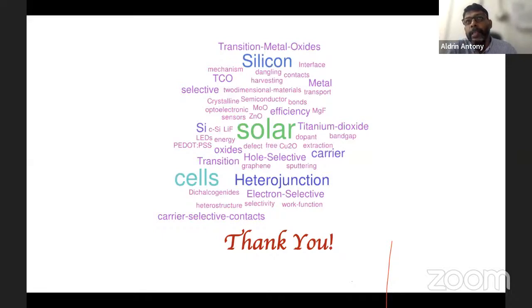But I don't see that thin films will come up. I feel like crystalline silicon will dominate the market because of the low cost in production and the large volume throughput that it is giving. But among the thin films, there will be perovskites coming up, which have a higher efficiency in combination with silicon, giving a very high efficiency of up to 30%, and still have a big chance as a major play in future.